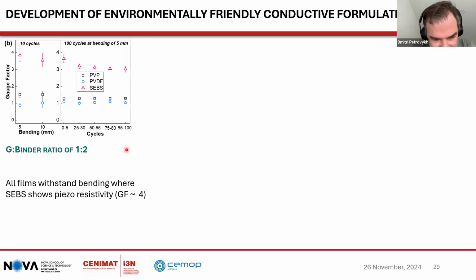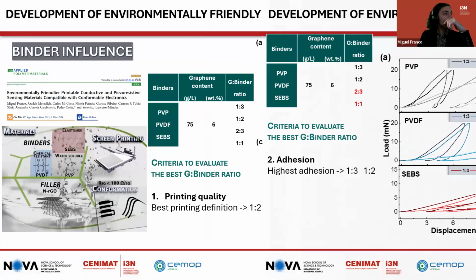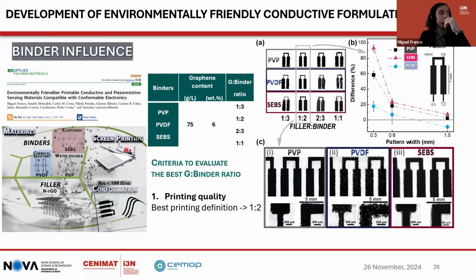All right. Another question: every method contains some other materials in the ink. Do these materials affect the printing process, and how can you prevent it? I guess in this case we're talking about additives or contaminants. For screen printing techniques, we tend to add additives to increase the viscosity of the ink itself and to give adhesion. However, there is a trade-off. If you put in a lot of binders, you can degrade the electrical conductivity, because you are forming composites in screen printing.